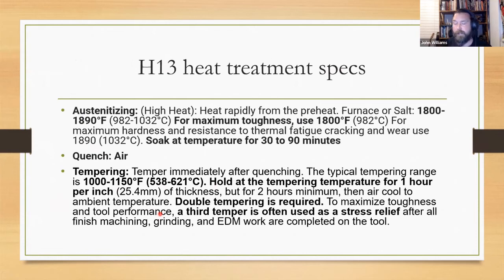And just to emphasize that, like I said, you can get a data sheet on all of these tools, on all steels, right? This is right from a tool steel manufacturer. So bringing this up to critical temperature, look at this range, 1800 to 1890. Well, first thing that you need to notice is that that's a lot higher than what was shown on that earlier chart. That's really, really hot. And you can do as low as 1800. It says air is the quench, meaning air is sufficiently, and this is why that chart, getting back to what Victoria said, sufficiently rapidly is the wording, because there's different rates of cooling that you need for different categories.